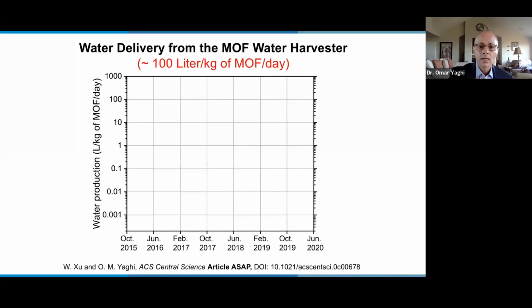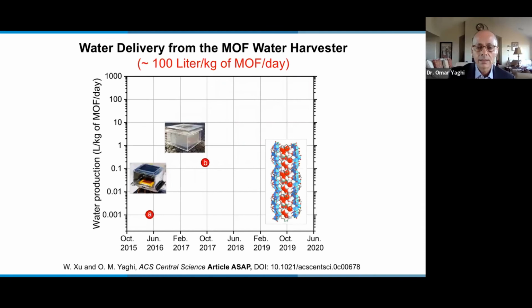US. So based on these results, it's very clear that using reticular chemistry, we can improve in a very short period of time the harvesting of water using MOFs. And once we have figured out a way of using the entire MOF particles that are in the material, we would be able to harvest for each kilogram of MOF 100 liters a day. Okay, and as I said before, the MOF does not have to be replaced. It can stay in the device for many, many years and deliver on a daily basis. If you have 1 kilogram of MOF, the expected delivery is 100 liters per day.